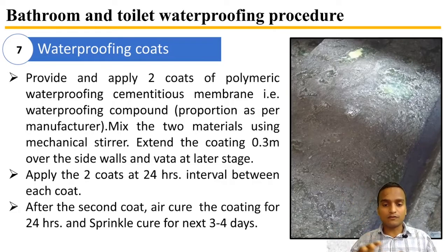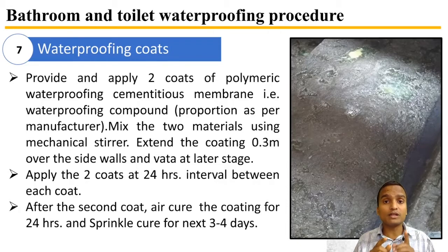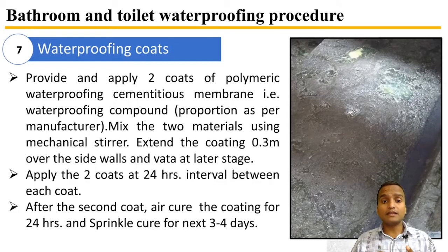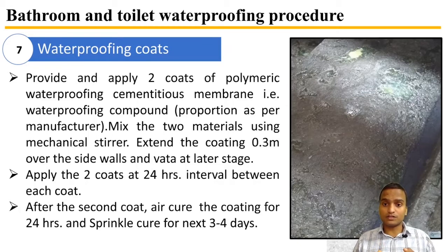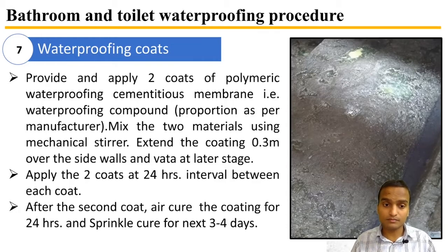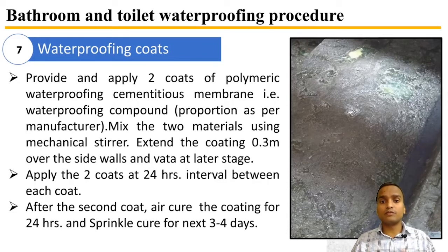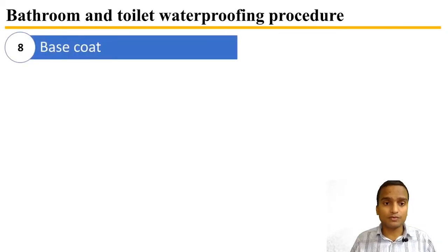After the first horizontal coating, a vertical coating is applied over the entire surface — both the floor slab and the side walls up to a minimum height of 300 mm. Two coats of waterproofing are applied with a minimum 24-hour interval between each coat. After the second coat, the surface is left for air curing, then water-sprinkled for curing over the next three to four days.